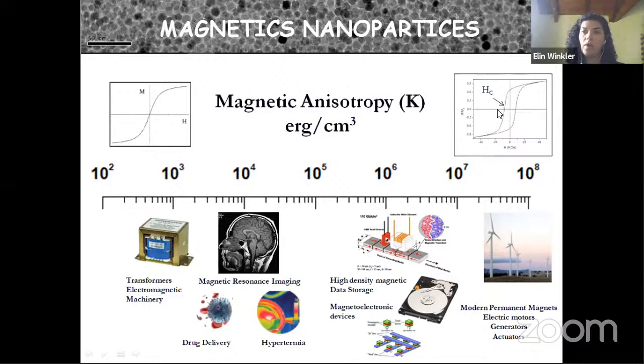And along the talk, we are going to talk about the hysteresis, the coercive field, which is proportional to the magnetic anisotropy in the case of nanoparticles. And this coercive field, we can tune it, and we can move from hard magnetic material to soft magnetic material. So remember that we are going to see several hysteresis cycles, and we are going to talk about the coercive field and the saturation magnetization.